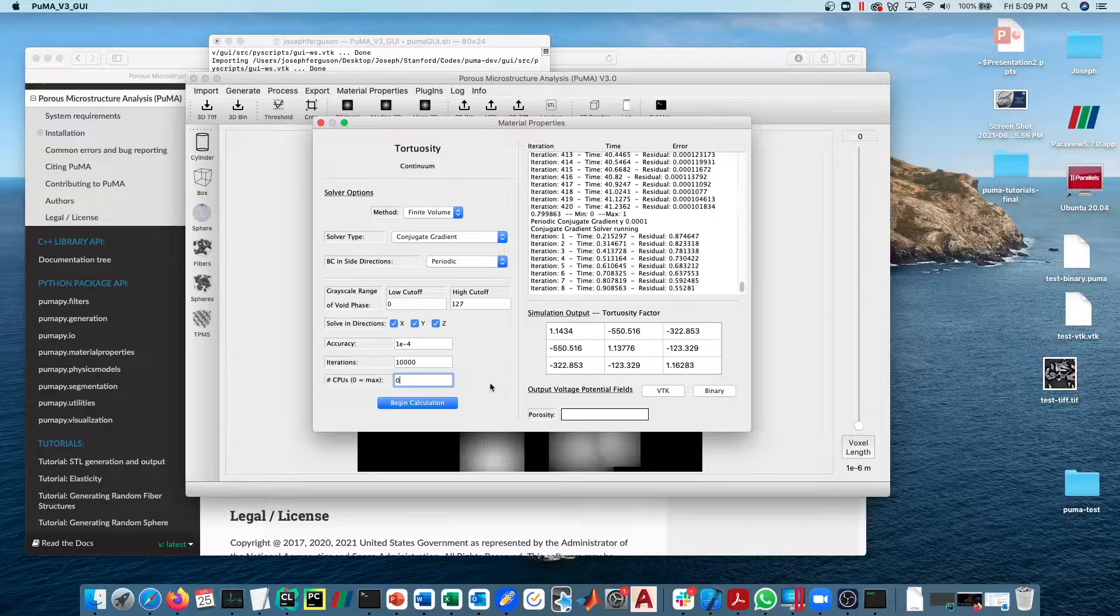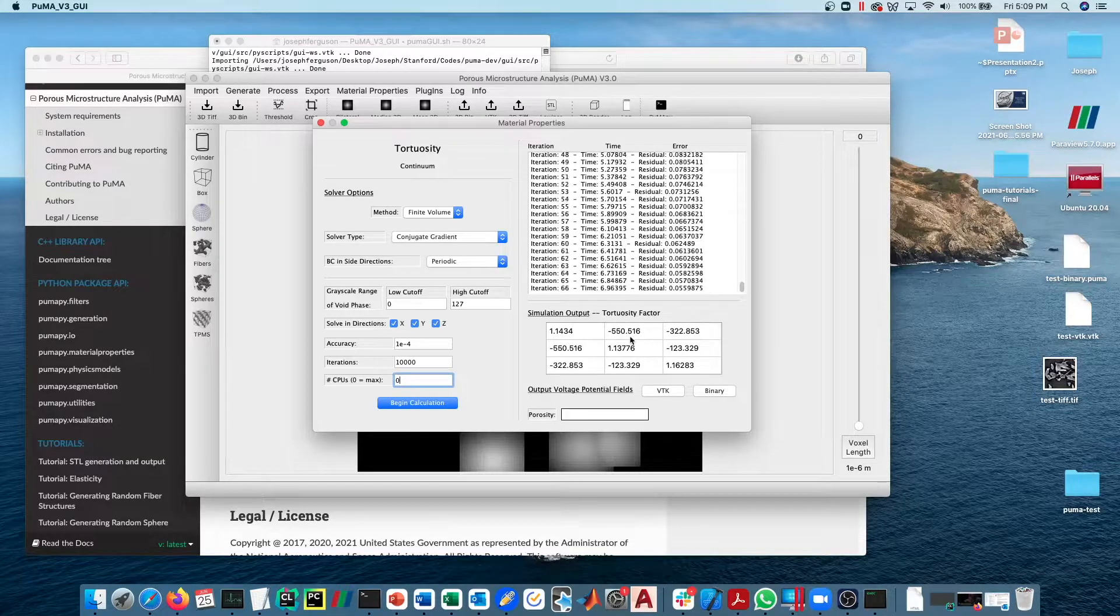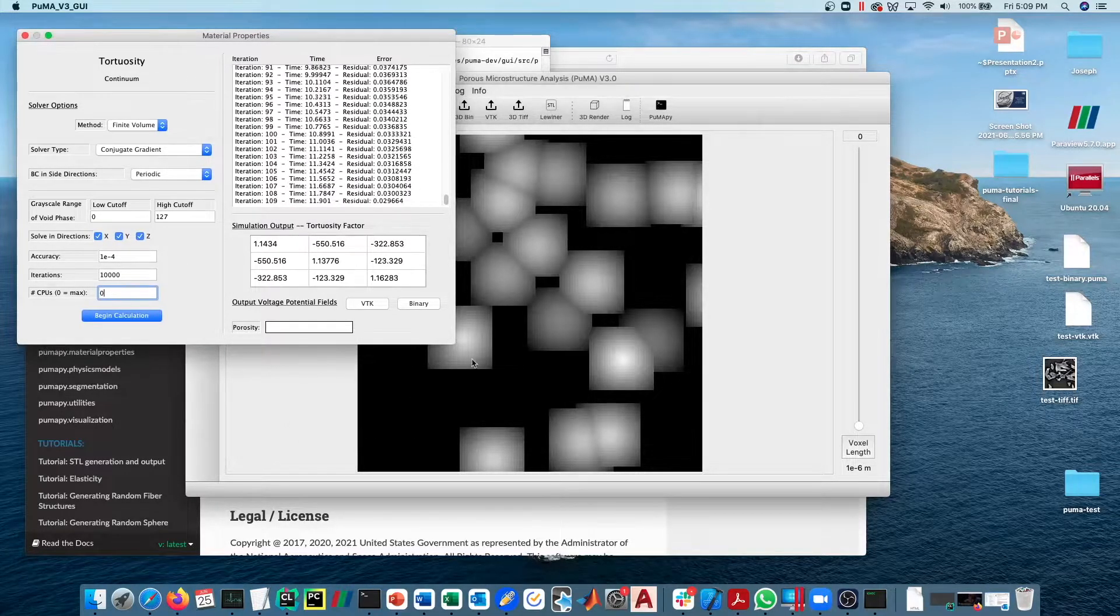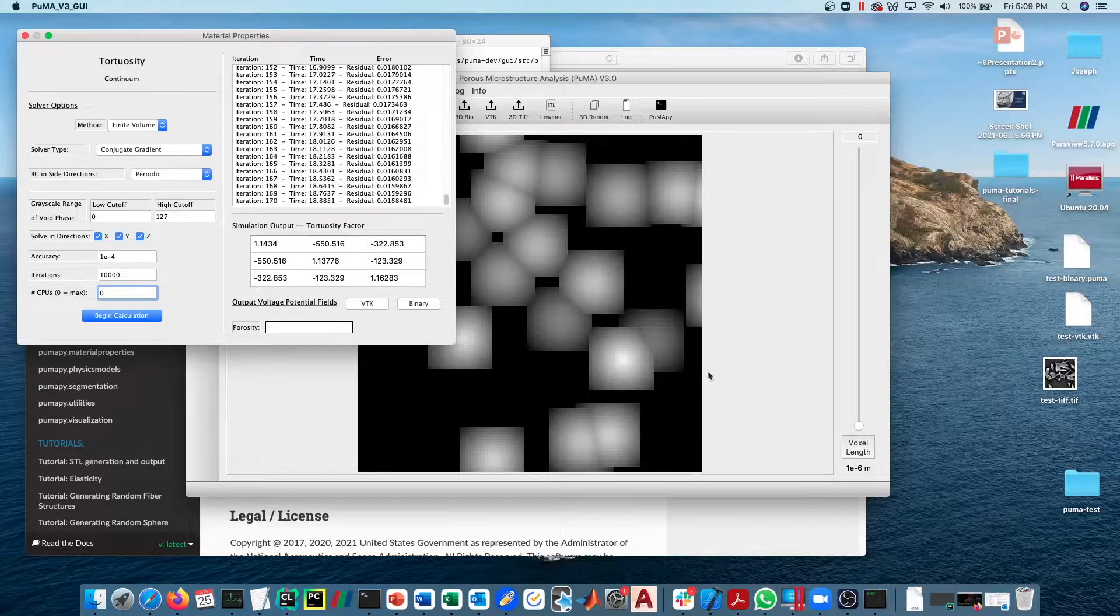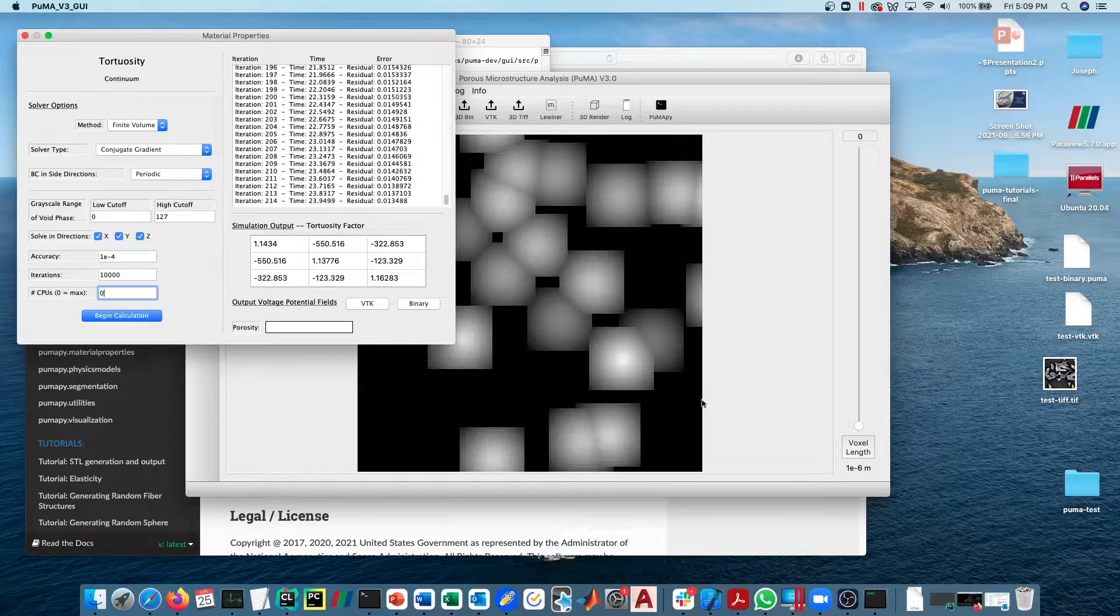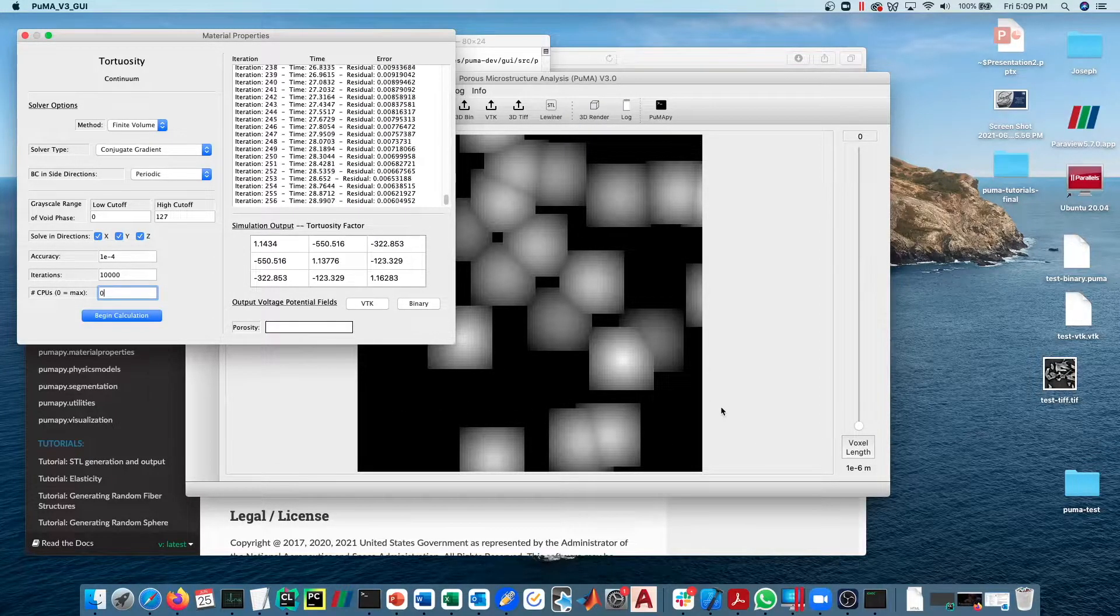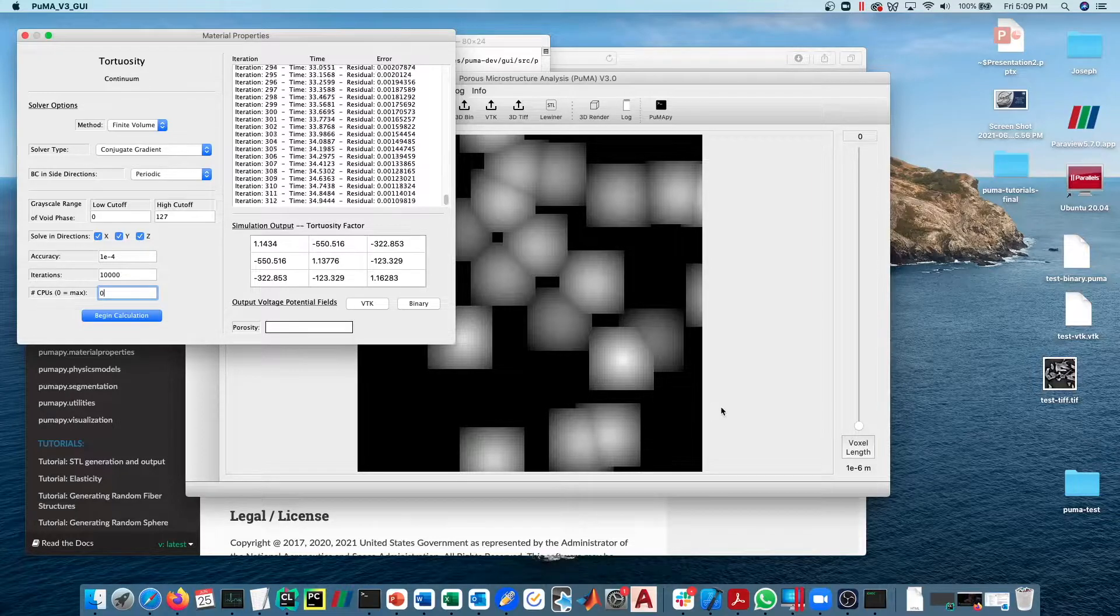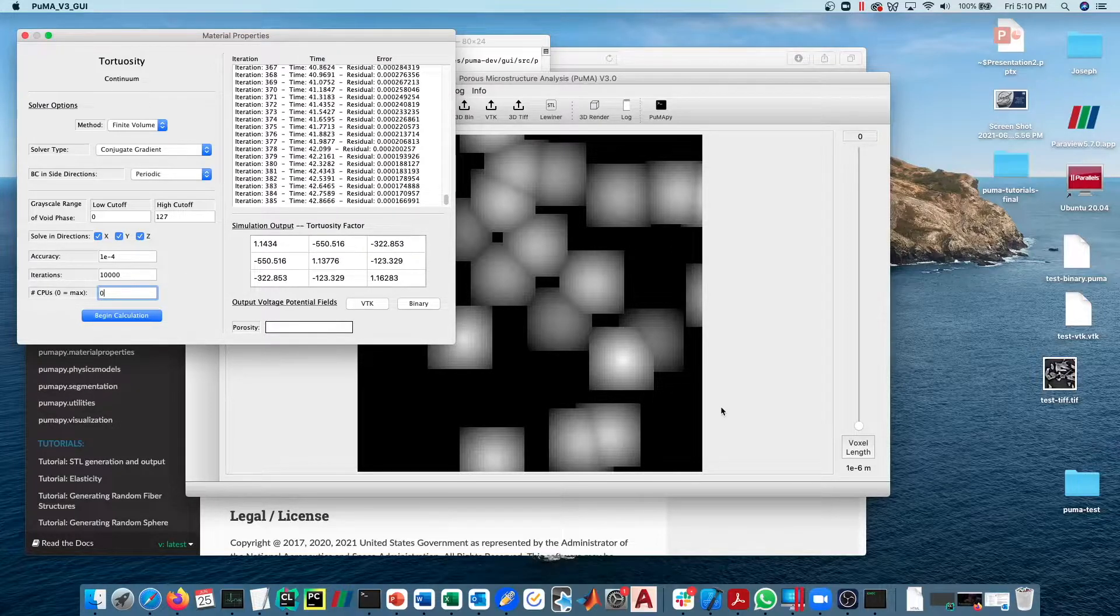There we go. The x direction is finished, now we've moved on to simulating in the y direction. I'll clarify what I mean by that. The way that this solver works is that we impose a concentration gradient in one direction. We'll impose, for example in the x direction, a concentration value of zero on one side and a concentration value of one on this side, and then the solver will converge the concentration field to steady state. Once it's done that, you can calculate the steady state diffusion flux, and then from the diffusive flux you can calculate the tortuosity value.